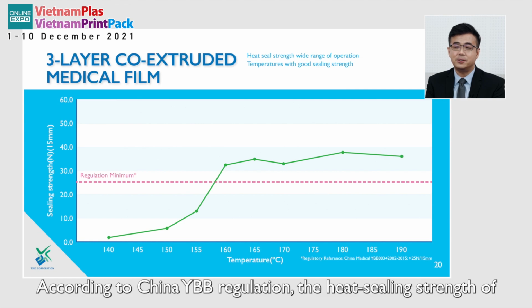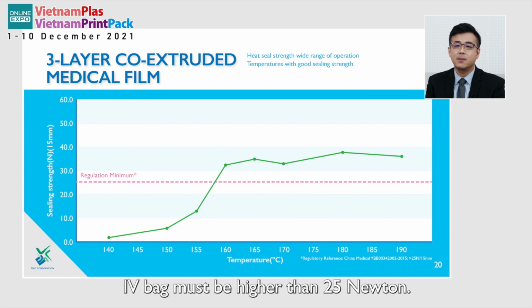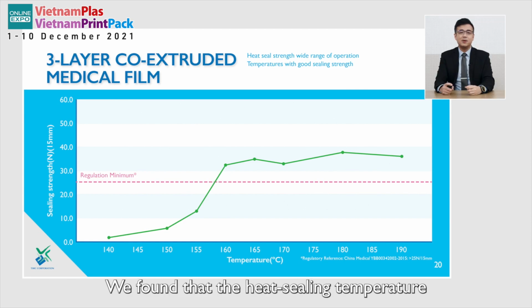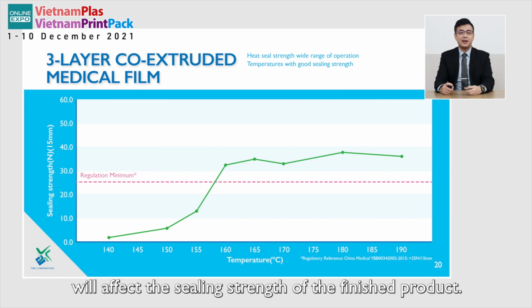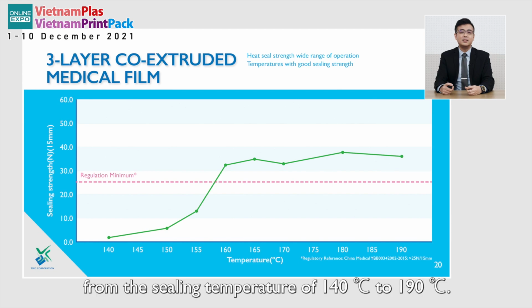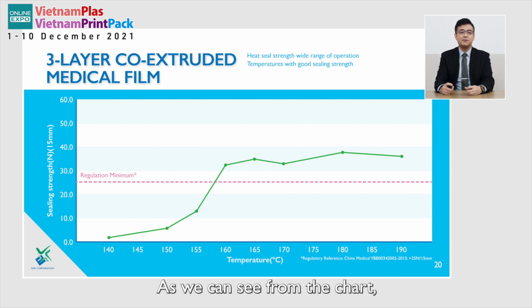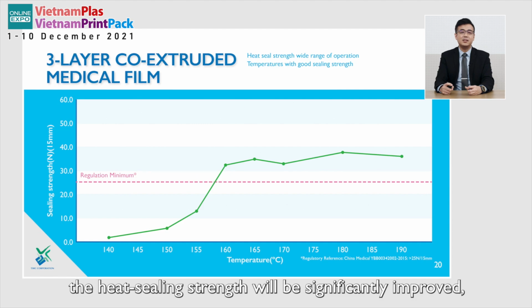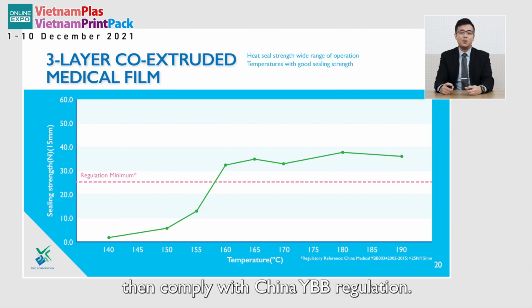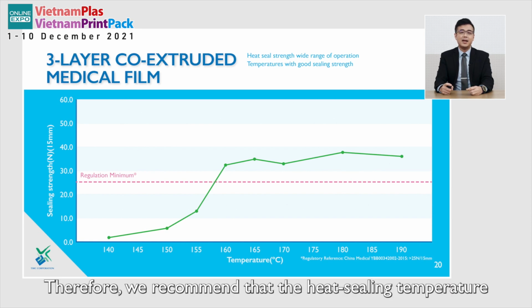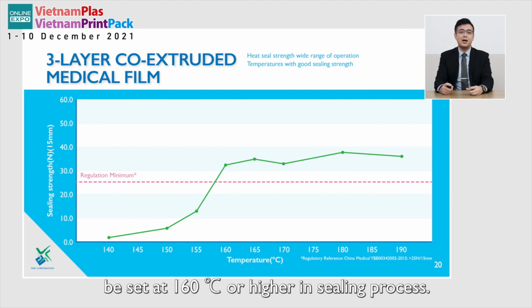According to China YBB regulation, the heat sealing strength of an IV bag must be higher than 25 Newton. We found that the heat sealing temperature will affect the sealing strength of the finished product. Therefore, we tested the sealing strength from a sealing temperature of 140 centigrade to 190 centigrade. As we can see from the chart, when the heat sealing temperature reaches or is higher than 160 centigrade, the heat sealing strength is significantly improved and complies with China YBB regulation. Therefore, we recommend that the heat sealing temperature be set at 160 centigrade or higher in the sealing process.